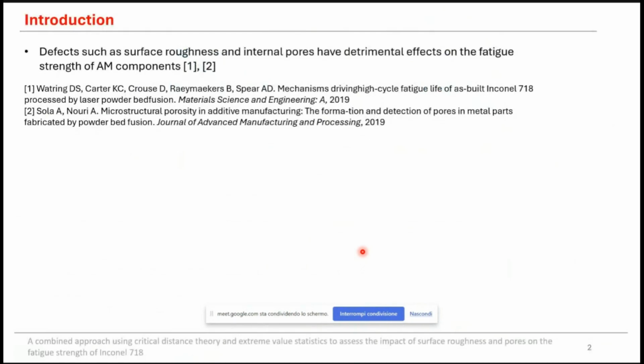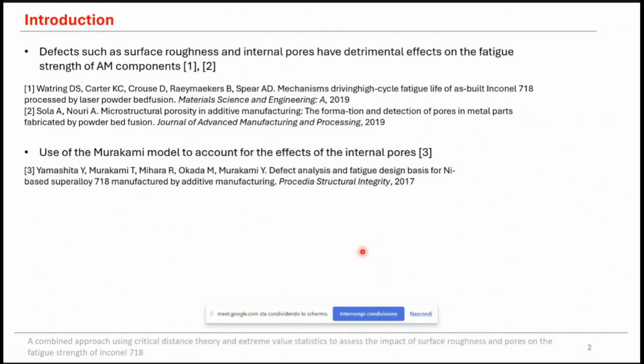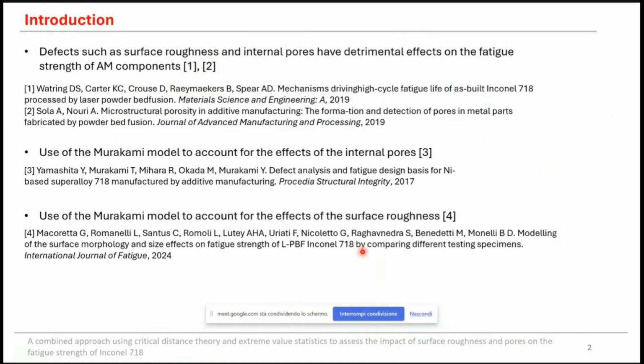Parma. As is well known from the literature, defects such as keyhole, lack of fusion, pores, and surface roughness have detrimental effects on the fatigue strength of AM components. Various techniques are available to model the impact of porosities, such as the Murakami model, which can also be used to model the impact of surface roughness.